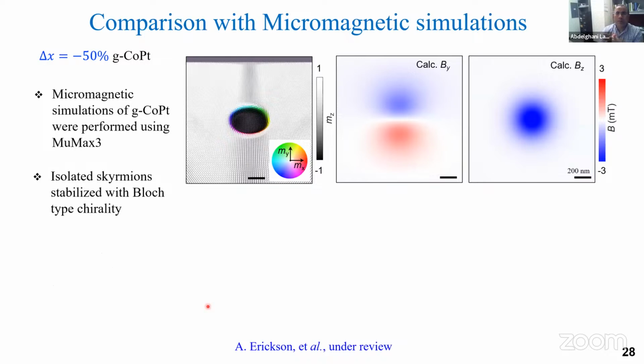So in principle, to know exactly what type of skyrmion we're mapping, we collaborate with Alexei Kovalev from UNL using micromagnetic simulation. We provide them all the magnetic properties of the samples, I mean the Ms and magnetic anisotropy, also from the bulk, from the SQUID and VSM measurements. Then they plug it into the model, and they found that in principle we can stabilize these Bloch-type skyrmions.